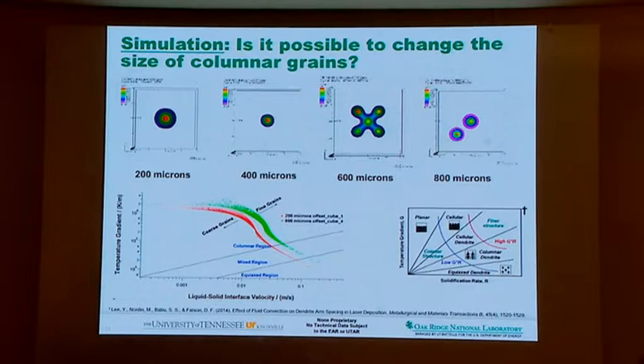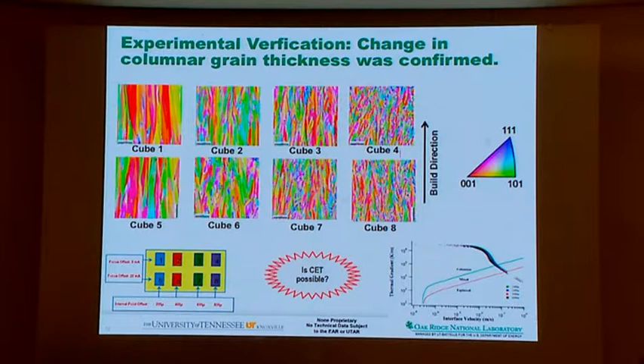So he ran numerical experiments, came up with the process parameters, and then used them to make experimental builds. In the same build, he could go from a very coarse columnar grain to a very fine columnar grain. You can see that from cube 1 to cube 8, he modified the grain size. Remember, there were no trial and error experiments. He did the modeling, came up with the process parameters, implemented them, and then saw this grain structure. Remember, I told him, I'll only sign your thesis if you show me that you can do columnar to equiaxed transition. So he took the challenge.